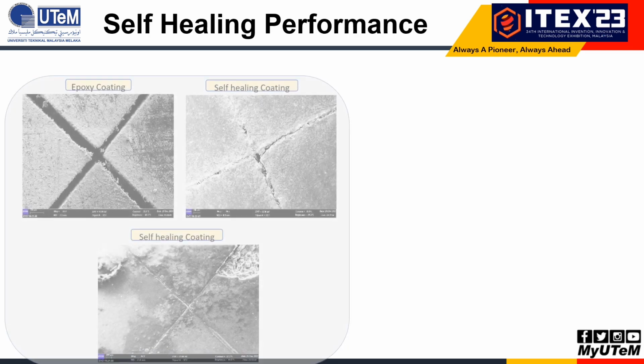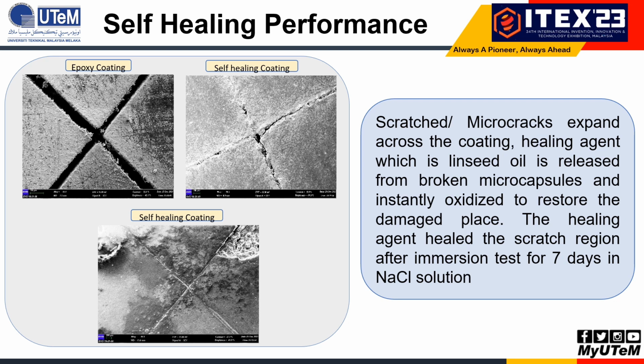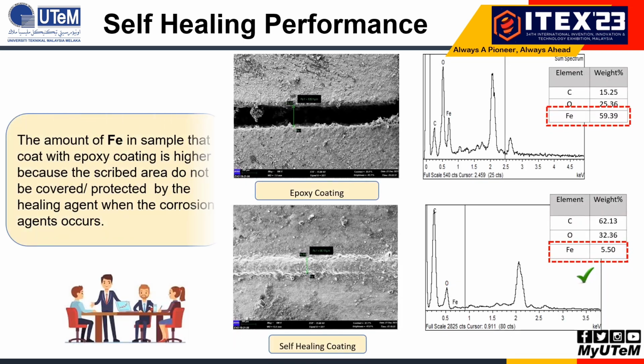Next, for the self-healing performance, as you can see on the screen, we have 3 samples: epoxy coating, self-healing coating, and then the result for the self-healing coating. Here you can see the 2 samples, epoxy coating and self-healing coating. The damaged surface area has been covered fully compared to the epoxy coating, and the amount of ferrum in the sample coated with epoxy coating is higher because the scratch area is not covered or protected by the healing agent when corrosion occurs. And then we have the difference in the weight percent of the ferrum for the epoxy coating and the self-healing coating, where the self-healing coating shows a much lower percent of ferrum compared to the epoxy coating.